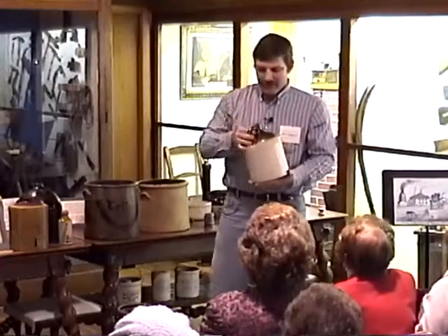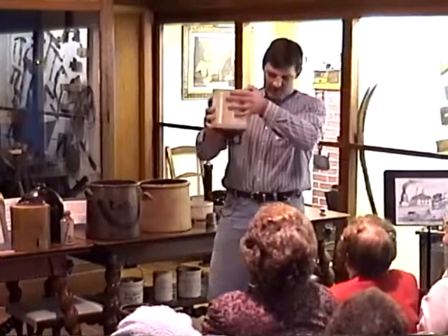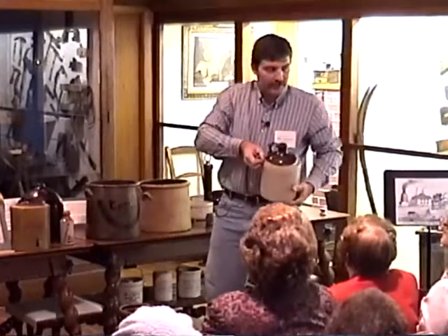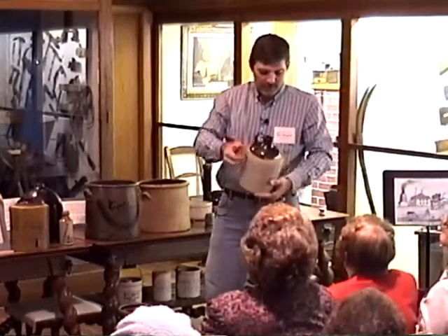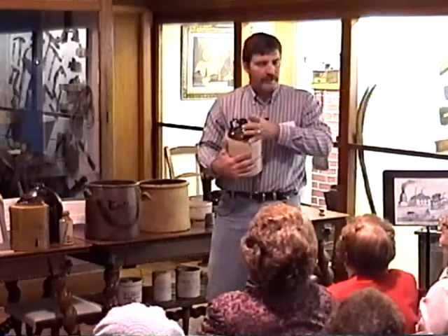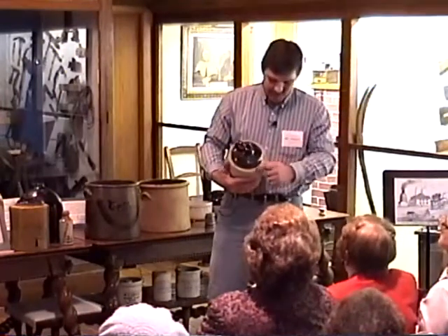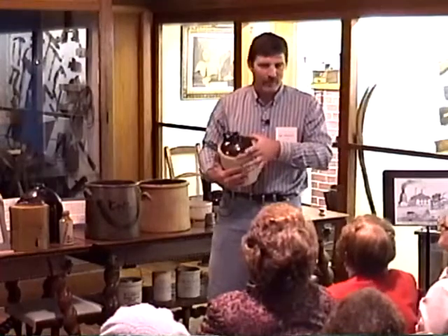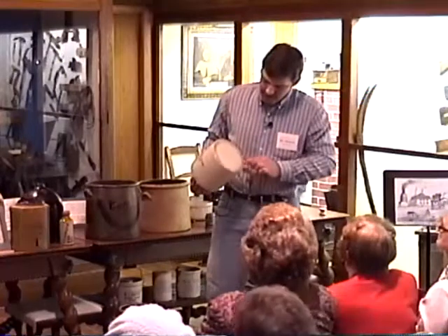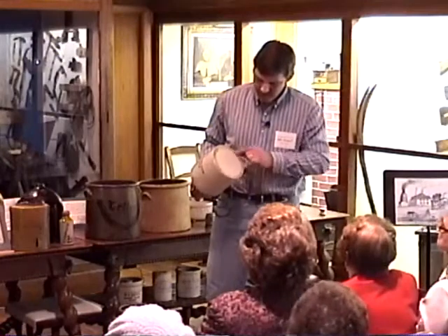Okay. So first they poured it inside, then poured that out, dipped the jug in deep enough to get the top glazed, took a sponge and cleaned off that shoulder. The main reason they did that is so they could stack a crock on there, because if that was glazed and they stuck a crock on there, it'd stick to it and they wouldn't be able to get them apart after the firing process. So that's why that shoulder is unglazed, so they could stack more items on it in the kiln. And the bottoms usually have a place where it's been wiped off, and this one the rim has been wiped off for the same reason. This is glazed, but the rim is unglazed.